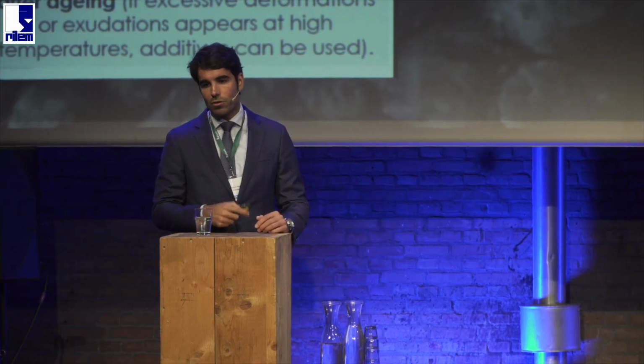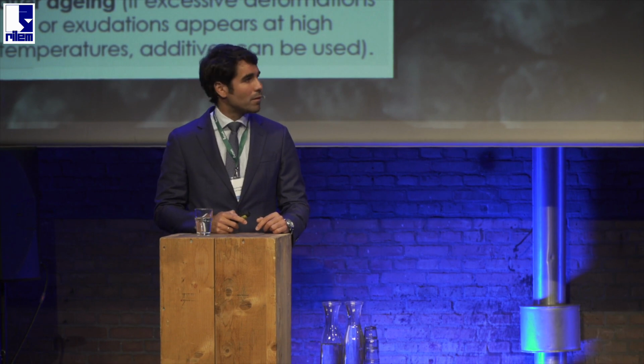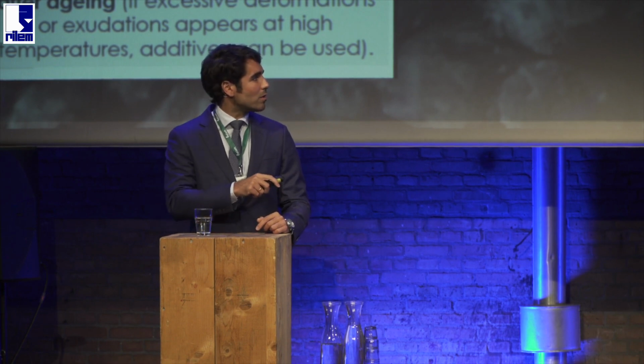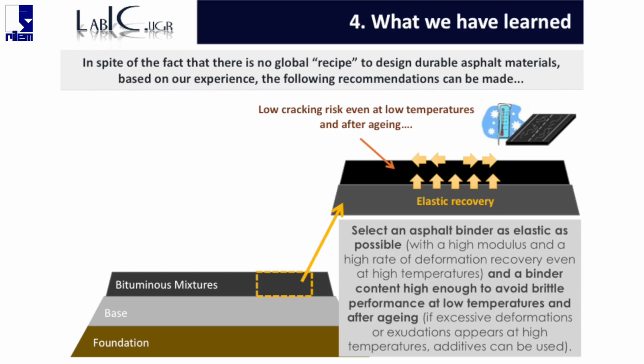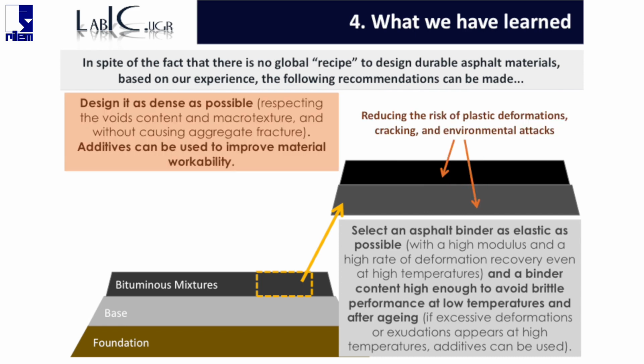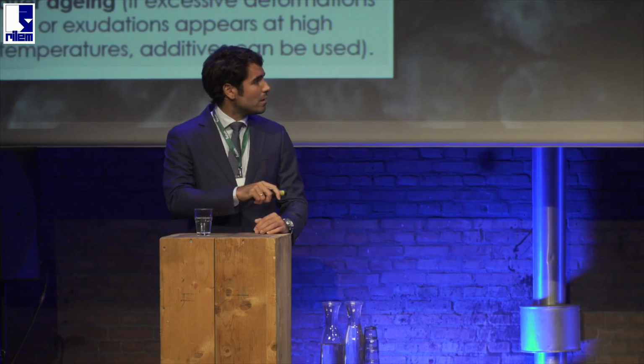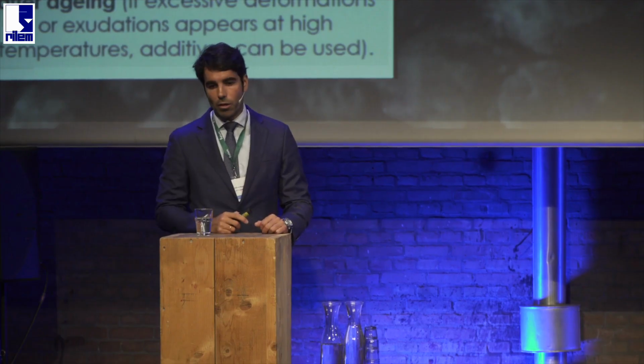For that purpose, we can use additives that improve the workability of the material, which help us to reduce the risk of plastic deformation, cracking, and environmental attacks. And finally, for sure, use pavement as thick as possible, but overall, try not to put an asphalt layer over another layer which is softer than the top one.